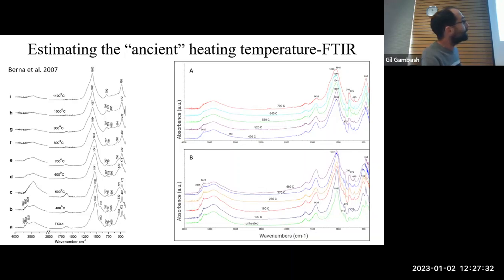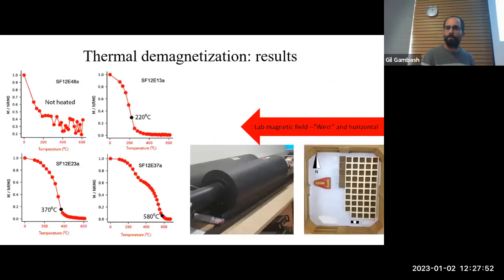At 520 degrees, you already see the significant change, the shift here in the main peak, etc. So 500 degrees and up is clear-cut that it was fired according to FTIR, but below 500 degrees, it's not always clear, and it's hard to tell if it was burnt. But it doesn't mean it wasn't burnt. It could have been burnt, but to lower temperatures.